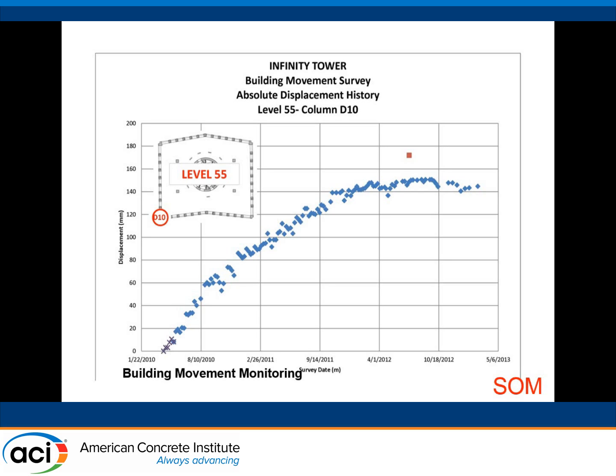But this is the kind of data we got out of it. And this was kind of nice to see. This was taken at a corner column at level 55, and you can see that as additional load is placed above level 55 and you've got the early strength concrete, you do get additional sort of twist movement in the building. But then it tails off nicely. And this is what we want to see. We want to see this plateau. It's certainly going to be a little bit unsettling if we don't see this plateau. And the red dot was our predicted data point for this particular column based on our creep and shrinkage and construction sequence analysis that we did.